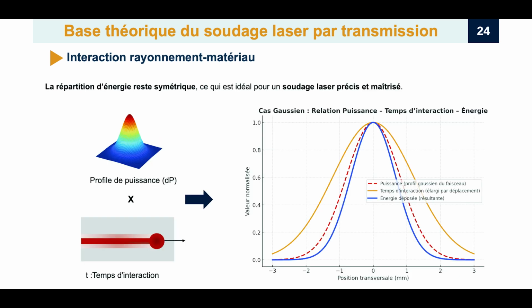When the laser scans at a certain speed, the exposure time T becomes highly non-uniform across the track width. Any point directly under the center line of the moving beam experiences the maximum possible interaction time, but points out towards the edges of the track see the laser for a much shorter duration, receiving minimal interaction time. So the time component T isn't flat, it actually looks Gaussian, peaked in the center. Precisely. The interaction time T as a function of position across the track follows a Gaussian distribution. It depends on the beam's diameter and how fast you're scanning. And because E equals P times T, even if your power P was perfectly flat, the total energy deposited, E, will still be non-uniform, peaking in the center.